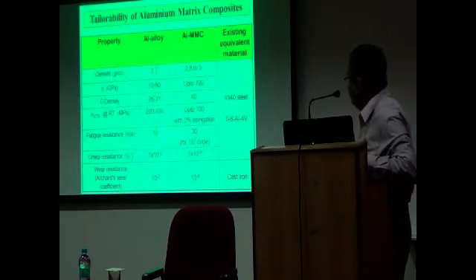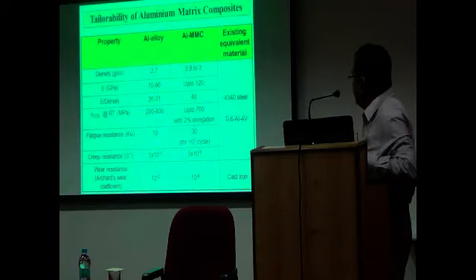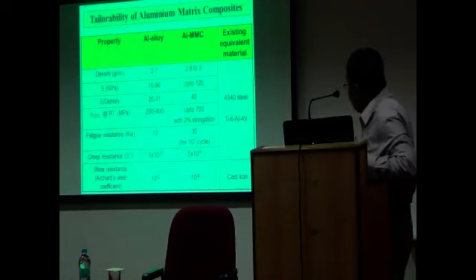If you look at these values here for aluminum, how much you can change? You can see the elastic modulus going from E70 to 80, and up to 120. The specific elastic stiffness goes from 26 to about 40, and the UTS up to 700. And these are properties which you can see only in steel and titanium alloys.